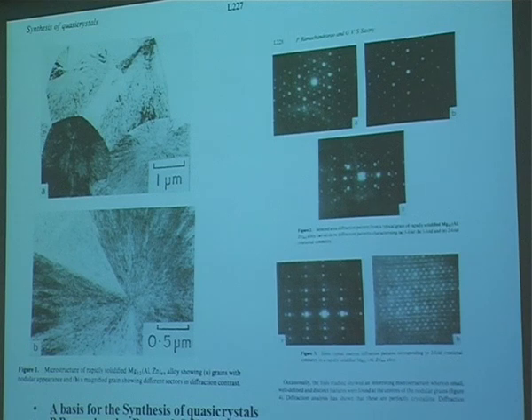You must go back to 1985, just a few months after the original discovery. We didn't quite know what quasicrystals are, what to do with them. Do they have an ordered arrangement or a disordered arrangement? What are they like, etc. And here is our friend giving the title, A Basis for the Synthesis of Quasicrystals. Many of us worked on aluminum systems because Danny showed that aluminum manganese alloys do that, so you change the percentage, 10%, 15%, 20%. The world over, many people were working. And here, Ramachandra went on a completely different track and took magnesium zinc aluminum alloys, and he shows the patterns, showing that you can get an icosahedral quasicrystal.